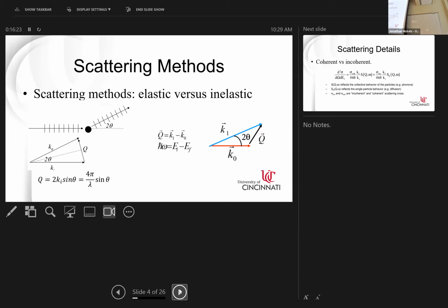So when you use neutrons versus when you use X-rays, you really should be needing to use contrast, or needing deeper penetration in your sample, or you need to do dynamics. That is when you would go to neutrons. Otherwise, X-rays are much faster, with very clean information. But again, if it's light elements, you don't have the contrast. So I'll show you a figure that sort of crystallizes that point.